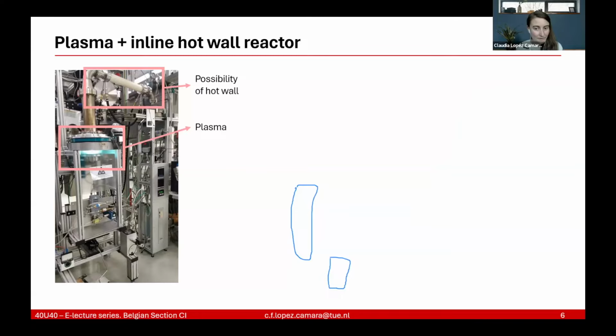Okay, perfect. And yes, so we also have the plasma synthesis, which is another kind of gas phase synthesis. In this case, we use a microwave plasma. That's what is pictured in the image. And this microwave plasma is the high temperature region, where we decompose the reactant that is already in gas phase. And there is also the possibility of adding a hot wall afterwards or another module of inline processing of the material.